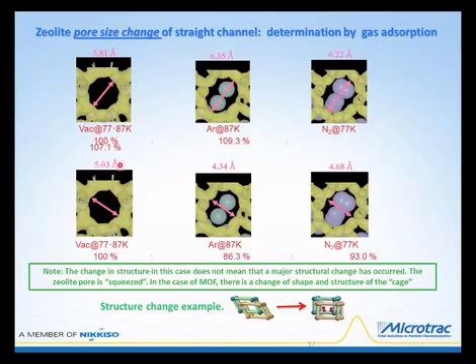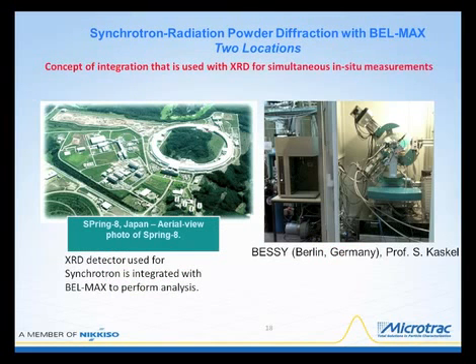So the next step is to look at the dimension orthogonal to the one up here. When we look at that, we see the basic structure of the MFI zeolite has a dimension of 5.03 angstroms, but then exposure to argon reduces that size to 4.34, and then finally over here to nitrogen. So there is a change in the dimension, but the whole structure of the MFI zeolite is not changing. This is the structural change that I was mentioning in terms of a real structural change. We're not seeing that, we're just seeing a change in the pore dimensions with MFI zeolite. But this was never known before, and it was assumed that no changes would occur. So this is the type of information that can be gleaned by doing adsorption and XRD simultaneously.